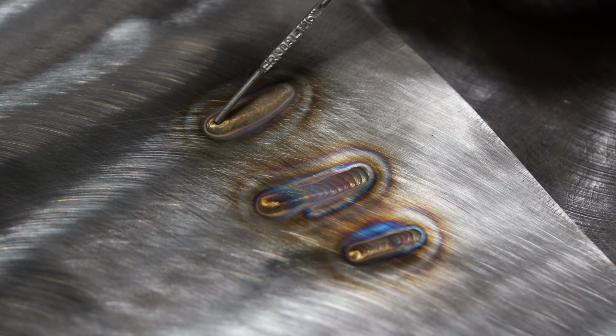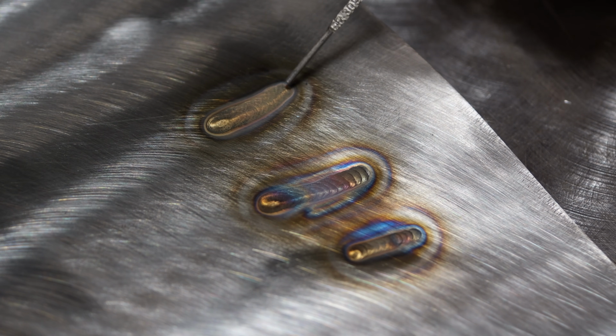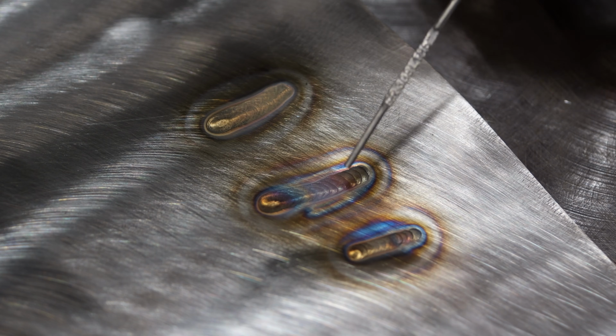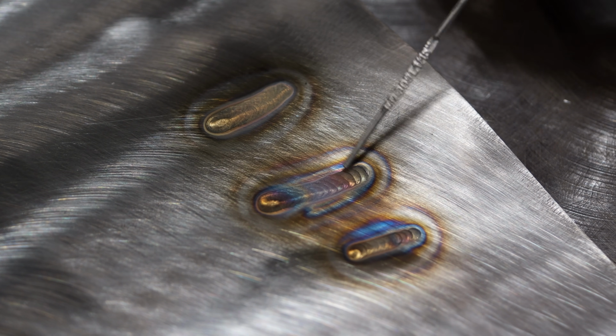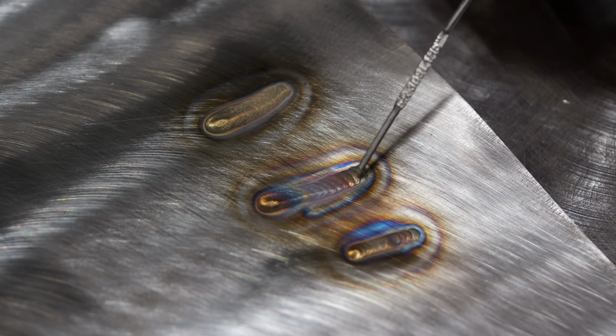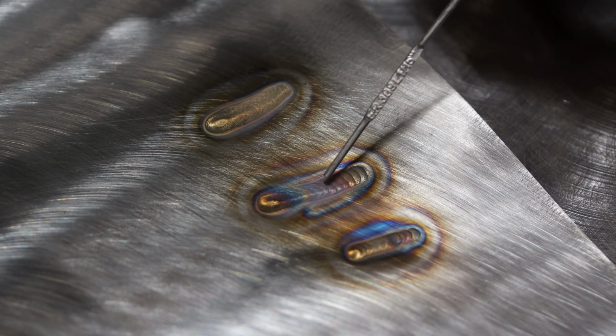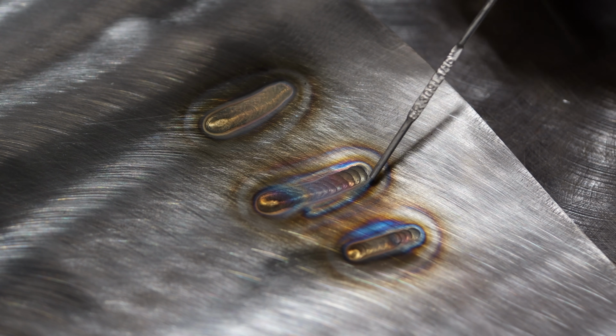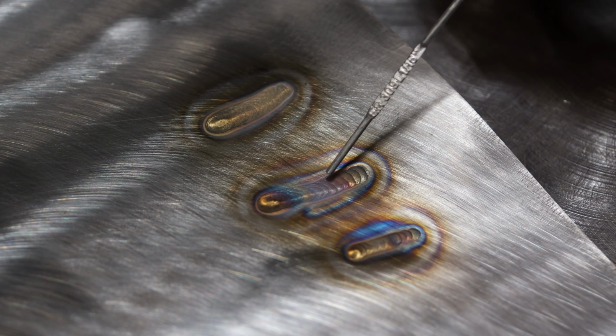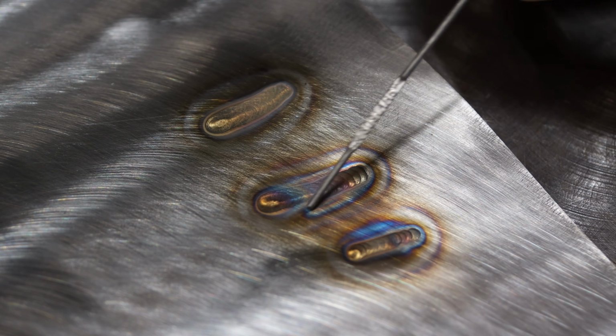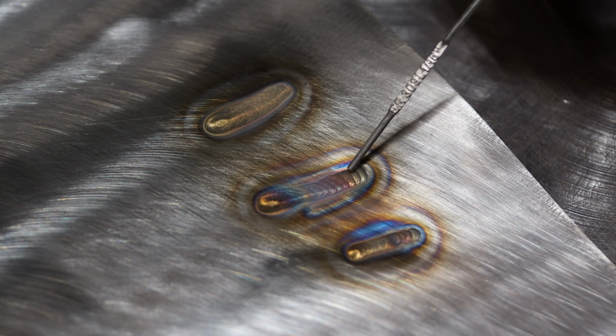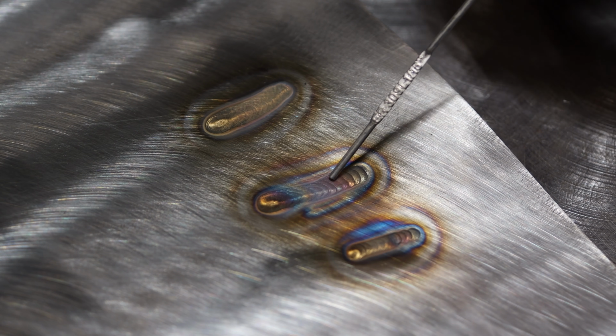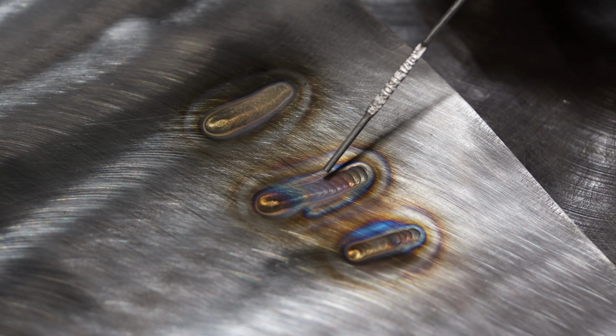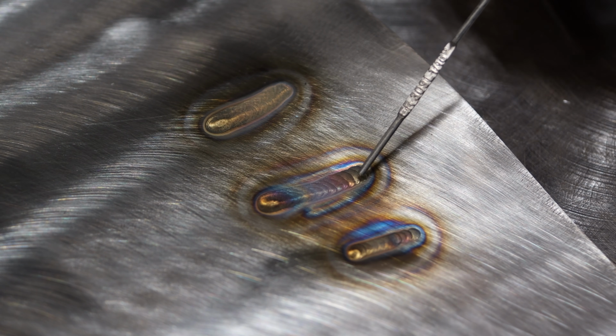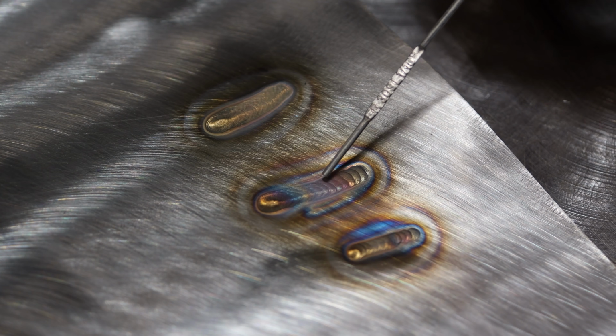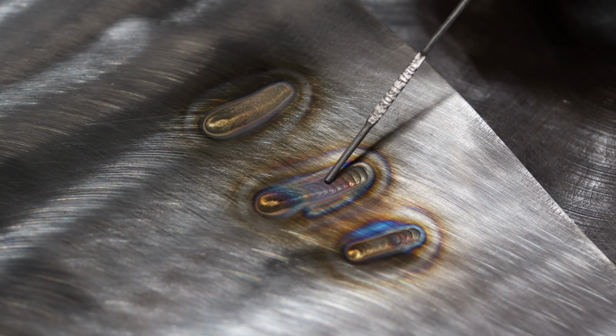As the tungsten is right here, this area is still shielded by that gas shielding envelope with the larger cup. When you get over here, which I ran at approximately the same foot pedal position, so the same amperage, just with a number 8 versus a number 14, as you're welding, more of this area becomes unshielded and reacts with oxygen simply because the gas shielding around that tungsten isn't as good. And that's why you start seeing, okay, this looks pretty good, and then over here it starts reacting with oxygen and turning dull red. Now, none of this is really what I would consider cooked, and I'll show you in a second when I buff this all off with a brush, it's going to look pretty good.